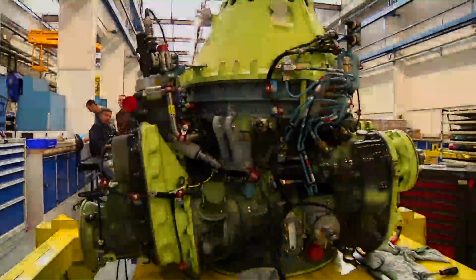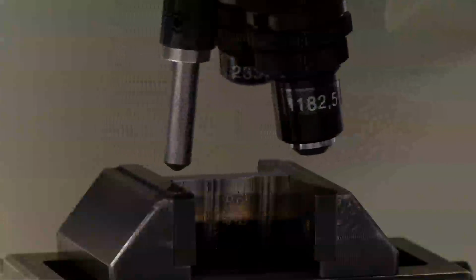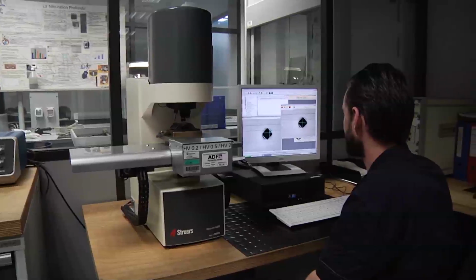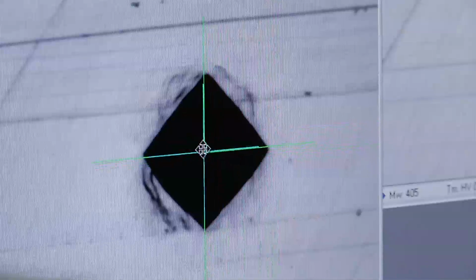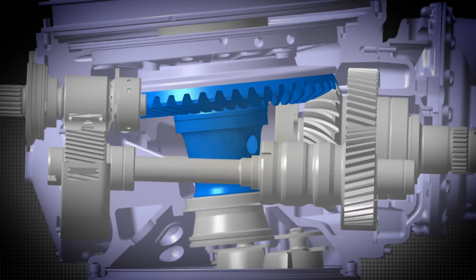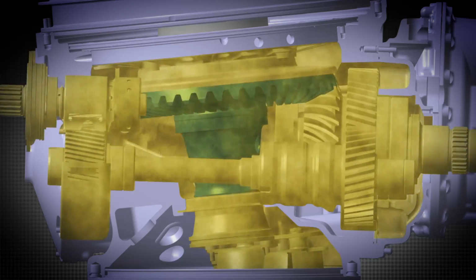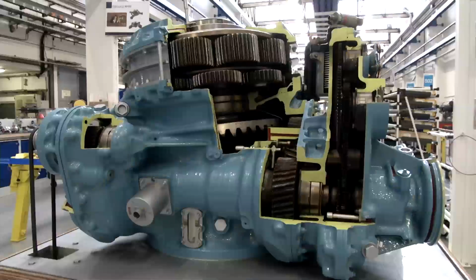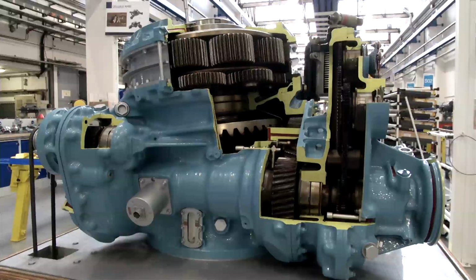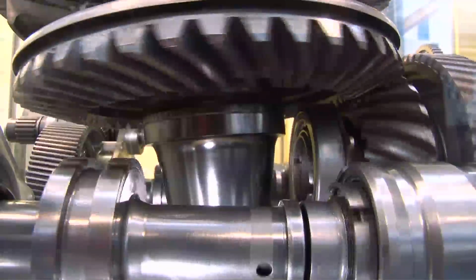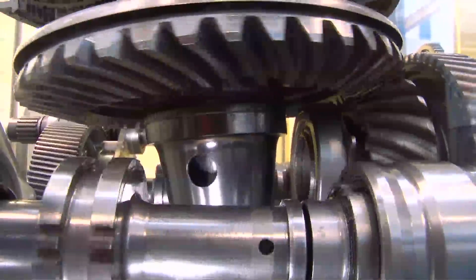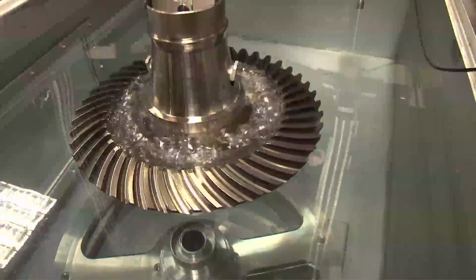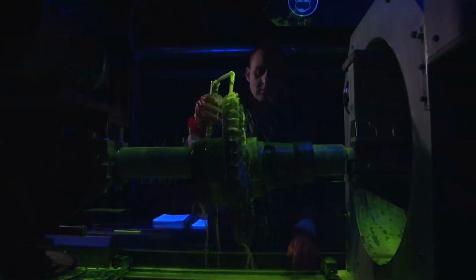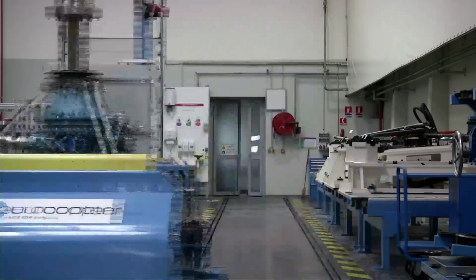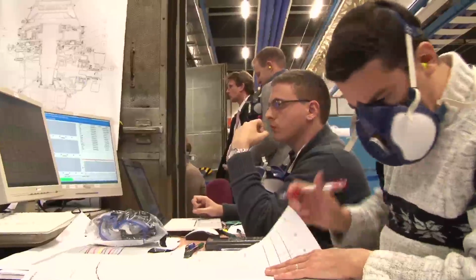Factor 3. Active corrosion. Detailed examination of the crack showed the presence of corrosion pits at the origin of the crack's initiation. Corrosion is an unusual phenomenon in a main gearbox, as all the parts are highly lubricated. The occurrence of corrosion is not enough to explain such a reduction of the bevel gear safety margins. So many tests have been conducted to identify the additional parameters that cancel the safety margins.